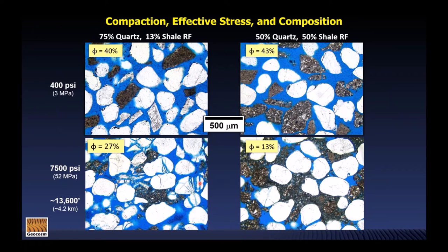Now this may look to you like something that doesn't look very realistic geologically, but what we found is that when you look at sandstones like this from nature in cathodoluminescence imaging, they indeed oftentimes show this type of fracturing. It's just not apparent in an optical thin section or optical microscope, because these fractures quickly fill in with quartz overgrowth cement and are very difficult to see without the aid of cathodoluminescence.